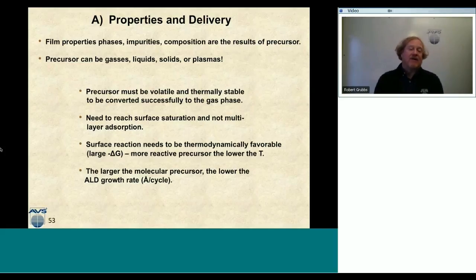And then, as I mentioned in the questions, the larger the molecular precursor, the lower the ALD growth rate. And I said rate there, I apologize, it should be growth per cycle. And that means that the real estate that this molecule takes up on the surface is going to limit the number of molecules on the surface at surface saturation. So when I bring this big organometallic molecule down, it sits on the surface, and then I react away all of that organic part and leave the central atom behind, my growth rates go down substantially. So you might see the bigger the precursor, the smaller the growth per cycle.